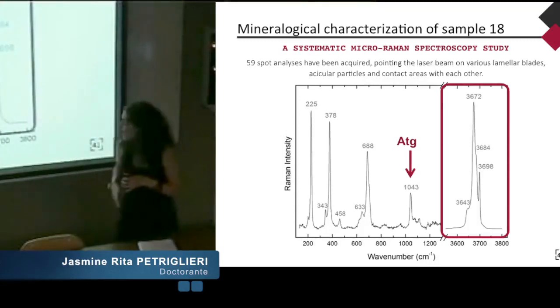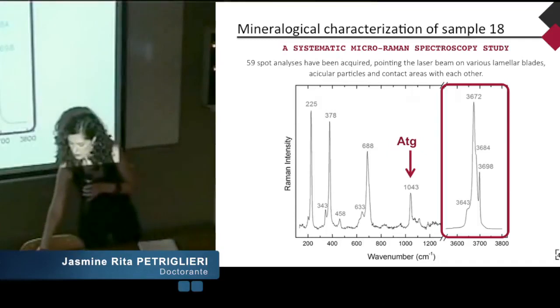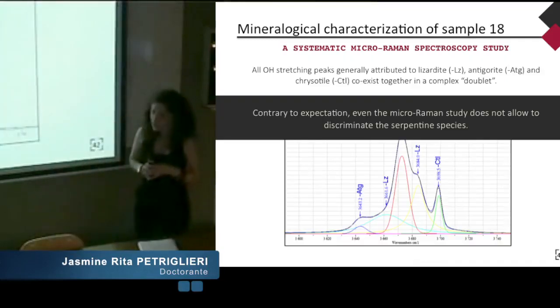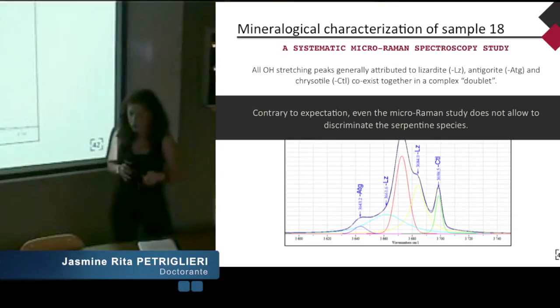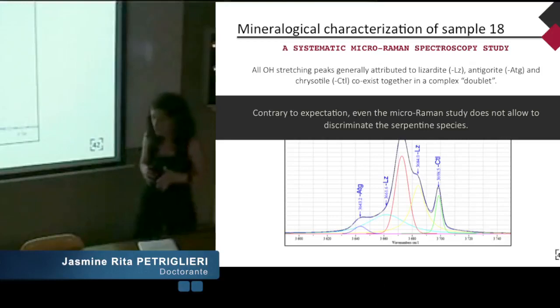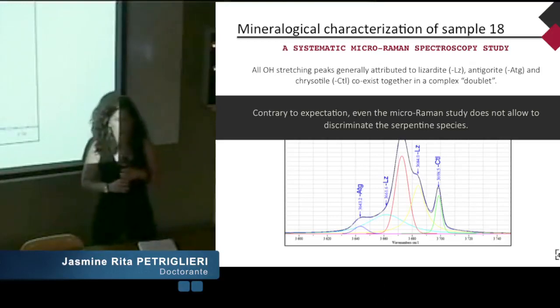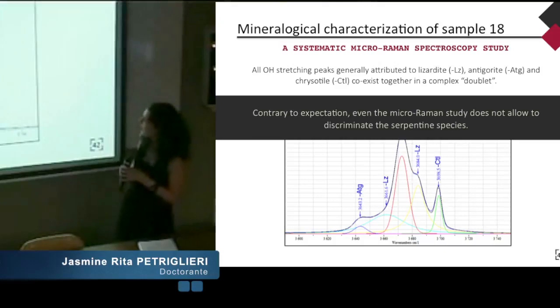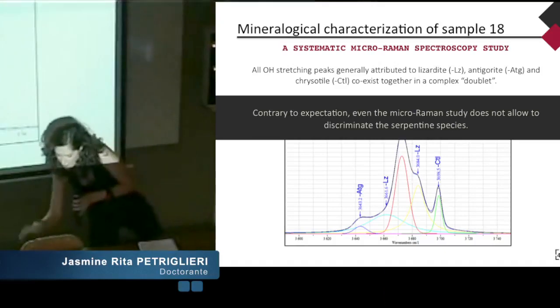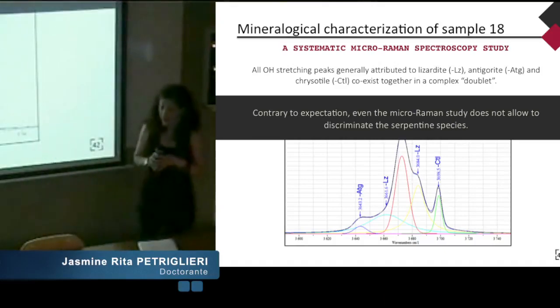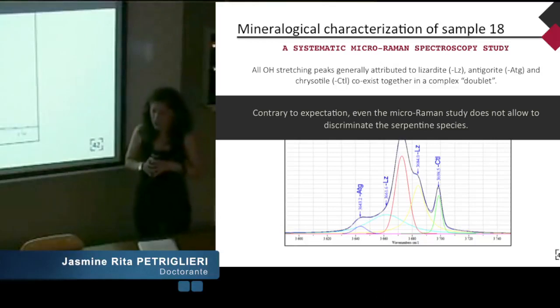Conversely, the OH vibration region demonstrates that all OH stretching peaks generally attributed to lizardite, antigorite, and chrysotile coexist together in the same sample to form a complex doublet. And it was the first time that I observed this complex, beautiful doublet. But even the micro-Raman study does not allow us to discriminate the serpentine species.